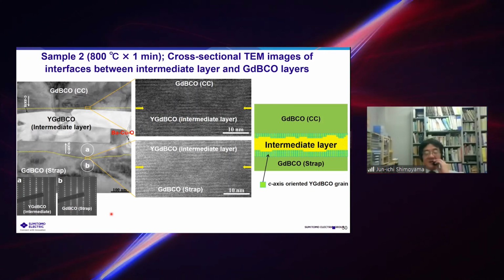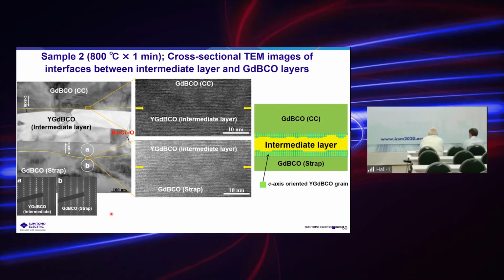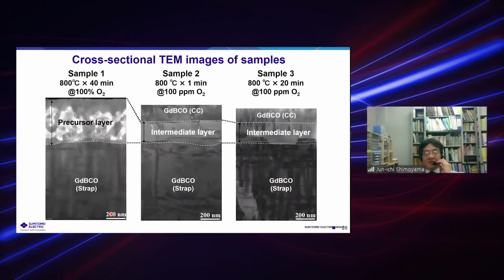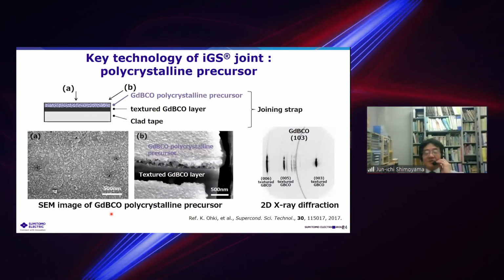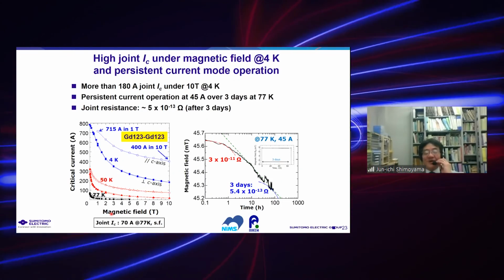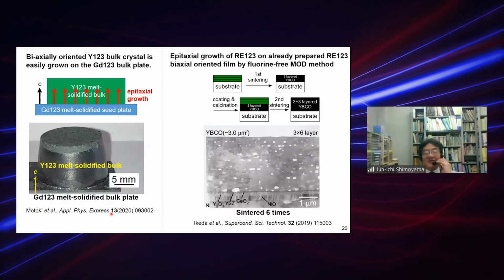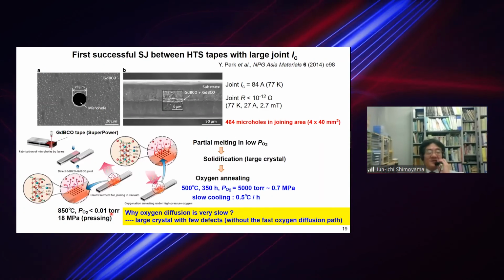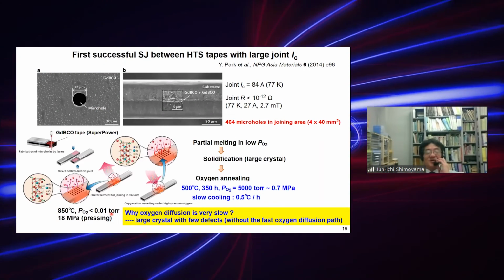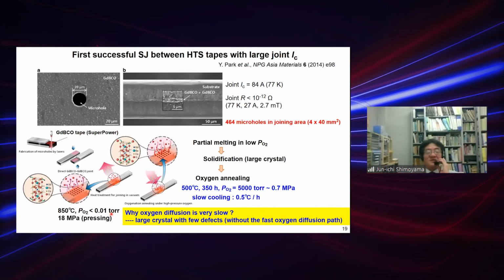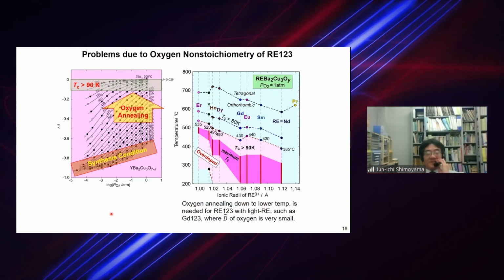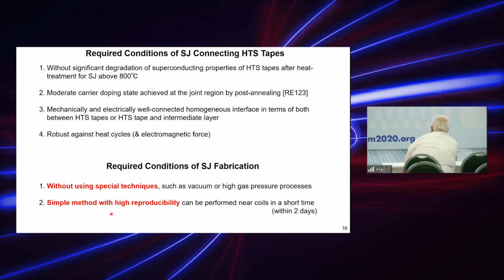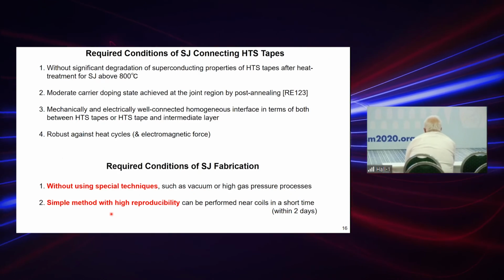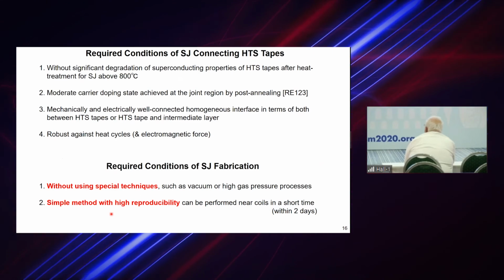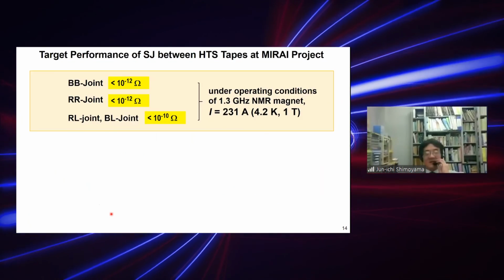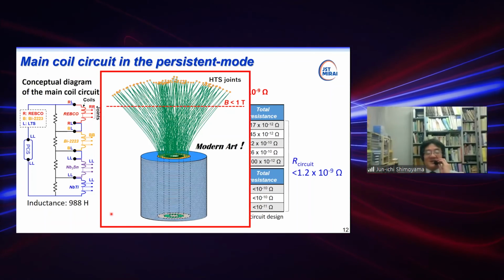Yes. But we must place a joint at the outside of coil. Outside of the coil? Yeah, because the electromagnetic force is very large when we put the joint at the coil. So the mechanical properties against the tensile stress is not good for both joints. Okay. Now the issue is that you can eliminate the effect of magnetic field on the joints with this arrangement. Yes.